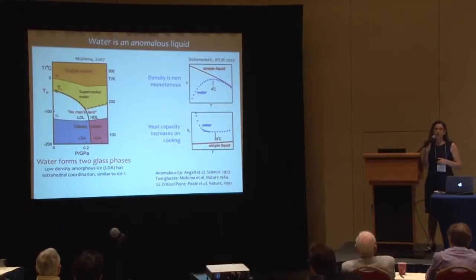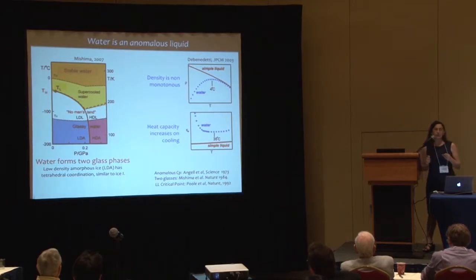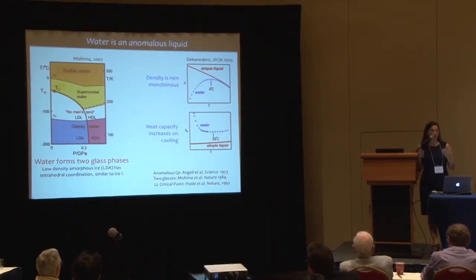We know more about supercooled liquid water when we look at the low temperature range and avoid crystallization. By extremely fast cooling — about 10 million Kelvin per second for micron-sized droplets — you can form liquid droplets of water into a glass state. This glass state, called low-density amorphous ice (LDA), is a four-coordinated glass that looks a lot like ice but is disordered. This glass can be compressed, and at low temperatures a transformation occurs to another glass — a transition between two amorphous states.